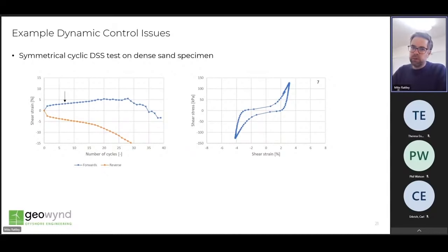The peak strains are still reasonably well balanced, but by cycle 15, as we see here, we see a significant distortion of the hysteresis loop, which is actually caused by a failure of the control system rather than anything wrong with the sample itself or any facet of the soil response to cyclic loading. In this example, the logging interval here is about 0.1 seconds. We can see, therefore, that the soil is deforming at a rate somewhere close to 100% per second. And at this rate, the control system simply can't maintain the stress targets until essentially the rate of deformation drops due to the increase in stiffness caused by dilation at higher strains.